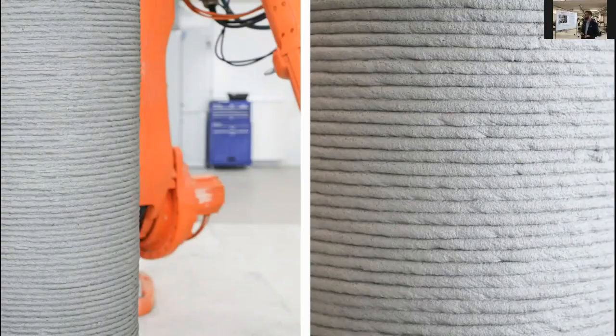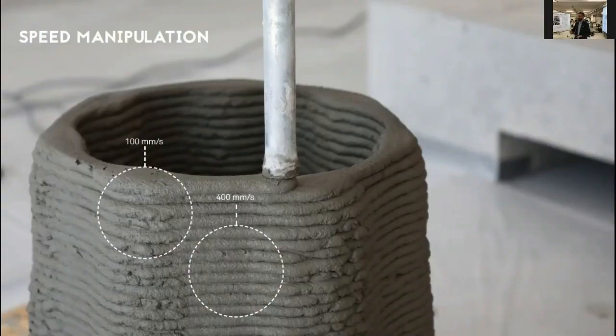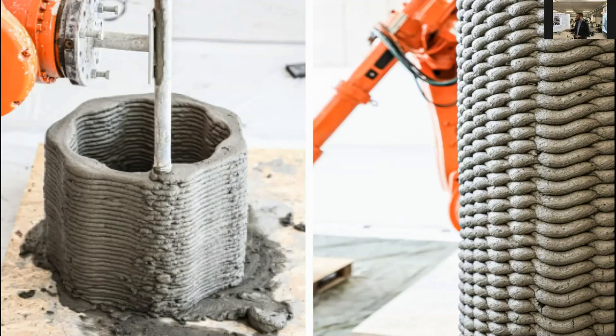You see here a layer height of 12 millimeters. So in comparison with before, we have a relatively high resolution. But also what you can get here is working with geometries such as this plain circular column, which has an almost smooth finish. You can still read the layers, but this is a regular geometry. You can also vary the thickness of the elements just by working with the speed of the robot, or with more intricate toolpath generation, as you can see on the right side, and get these decorative elements, which also allow you to gain other mechanical performance.